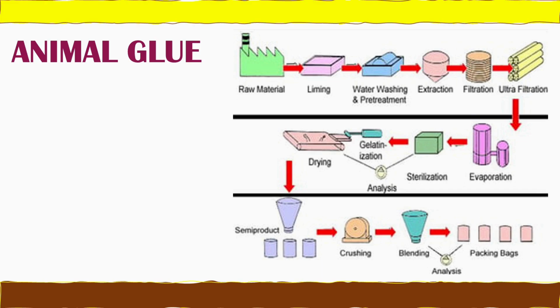So basically what is happening over here, we are taking the raw material, small splits or the trims of the hide, and then we are undergoing some pre-treatment process using water and lime, soaking for a few weeks, so that the extraneous protein related materials get removed and we get the hide cleaned up. Hydrolysis is done, and after hydrolysis the collagen that we obtain is conditioned, washed with water, and then acidulation is done, or alkaline treatment if required.